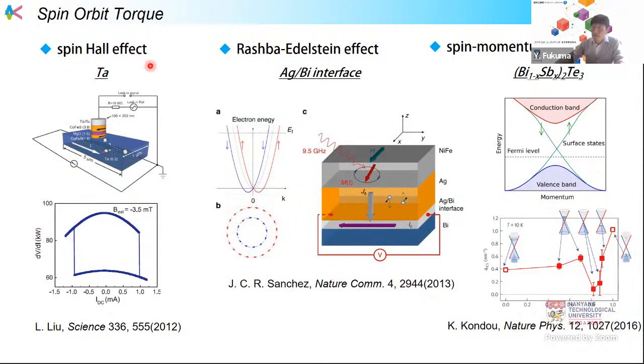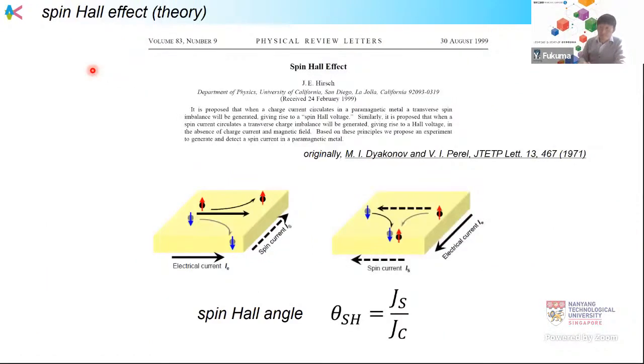But in this study, we mainly want to focus on the spin Hall effect because of the bulk effect. The spin Hall effect was theoretically predicted almost 2 decades ago. The original work is more than 40 years ago. The important message from the prediction is that the direction of the charge current, the spin current, and the direction of the polarization are orthogonal to each other. And we call the conversion efficiency between the charge current and the spin current the spin Hall angle.